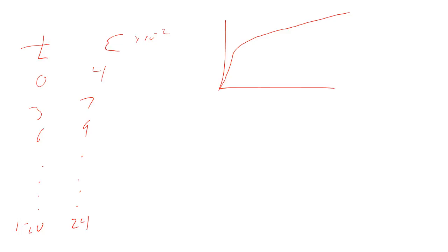If this curve actually becomes linear like this and keeps increasing with constant slope forever, it's not viscoelastic at all, because it's not recoverable. No matter what I do, I will always have a permanent plastic offset.